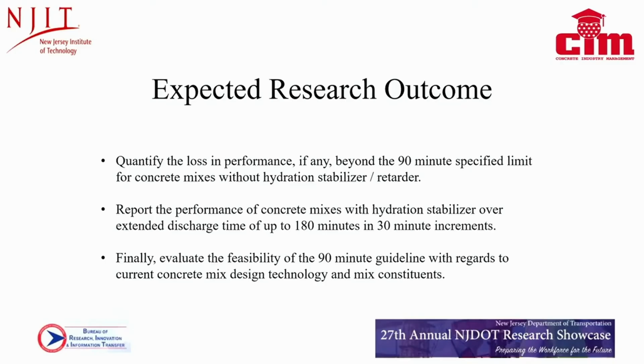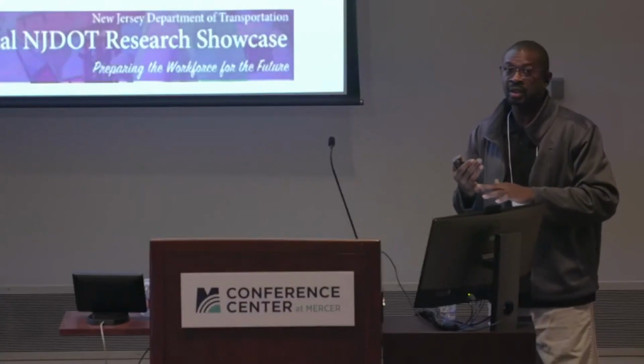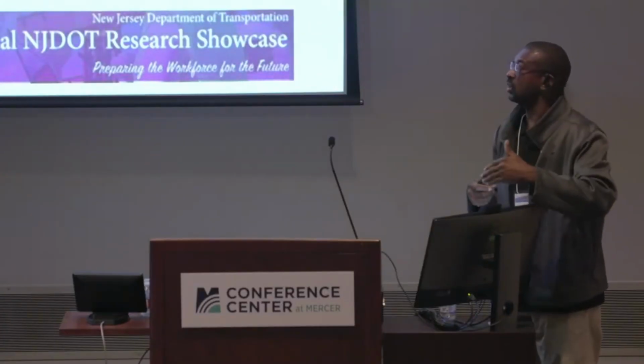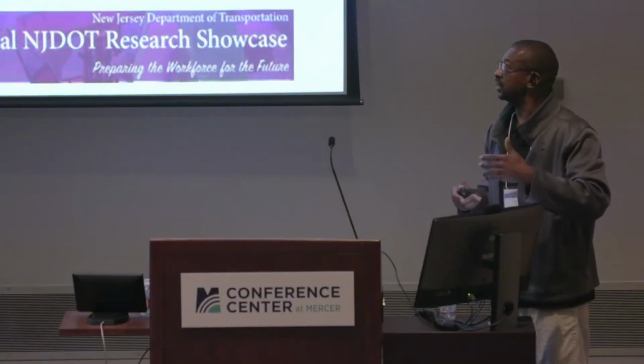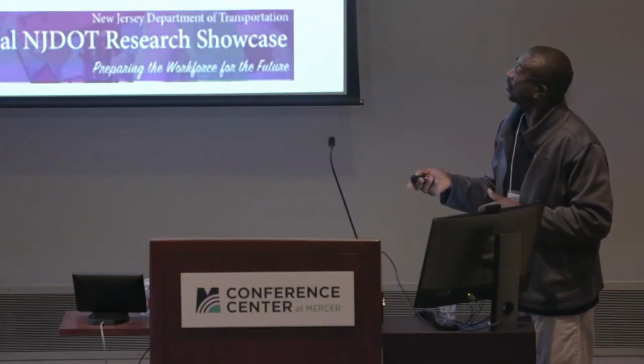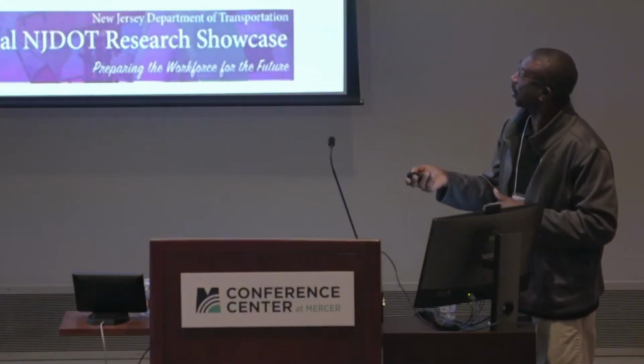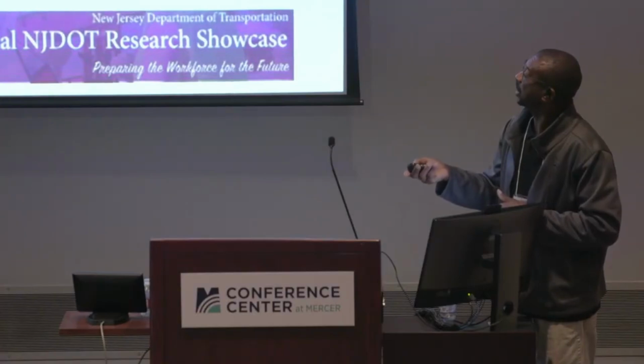So one of the things we did, like I said, there were different parameters, different criteria that we used. Summertime, fall, so hot weather, moderate temperature. We also utilized hydration stabilizer and without hydration stabilizer. Also to note is that the only modification we did to the mixes after the initial mix were with the high range water reducer and air entrainment, because naturally as the mix continues, it will tend to lose air, and we wanted to maintain that air, 6% I think it was, air entrainment level.